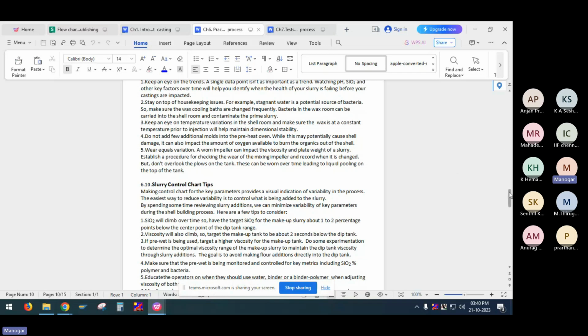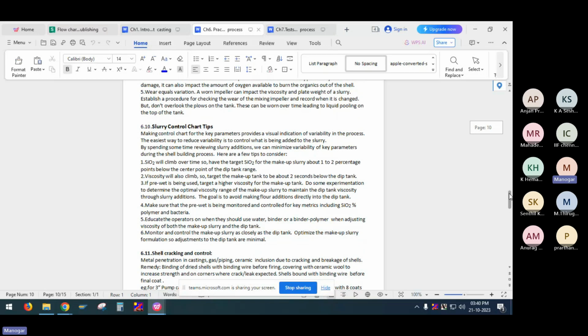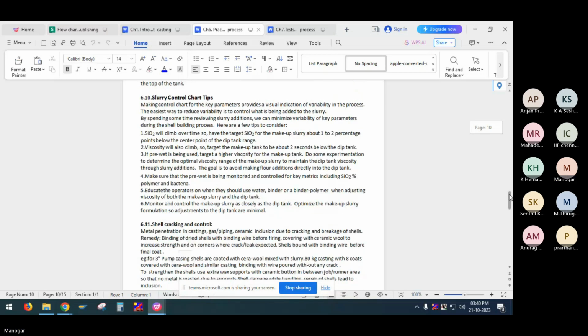Slurry control chart: follow slurry control charts to monitor the trend. For example, the silicate content will climb due to variation, going above the target SiO2. Keeping the slurry about 1 to 2 percentage points below the center point of the dip tank is important. Viscosity will also change during continuous coating, so you have to monitor the viscosity also. And pre-wet is also monitored.